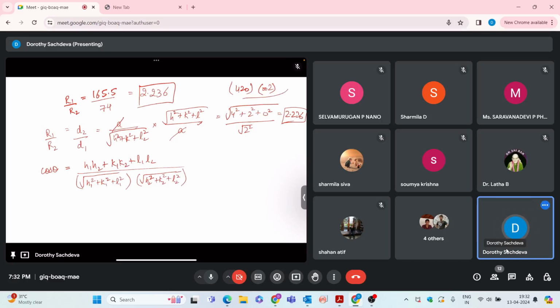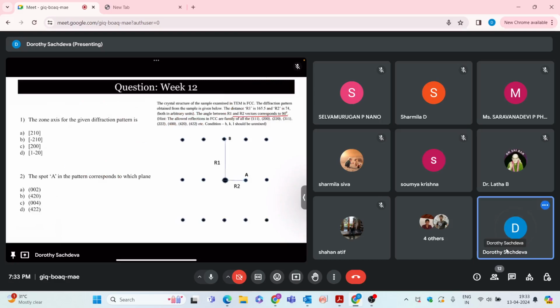So when you are taking these two planes, just put the values of h1, h2, k1, k2 and l1 and l2 from 4 2 0 and 0 0 2. So cos theta will become 0 only. 4 into 0, 0, 2 into 0 and 0, 0 into 2 will be 0. So according to this, theta will be 90 degree, which was given in the question, that the angle between r1 and r2 vector is 90 degree. So according to this, the zone axis is 0 bar 2 0 and the plane of spot A will be 0 0 2. And we have confirmed it using different techniques. This is clear to everyone?